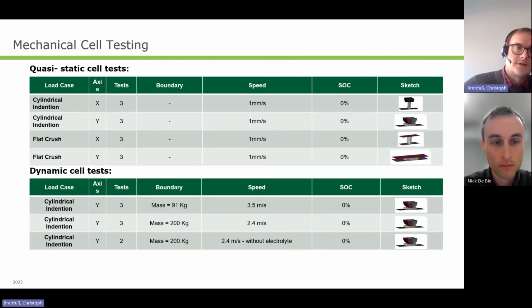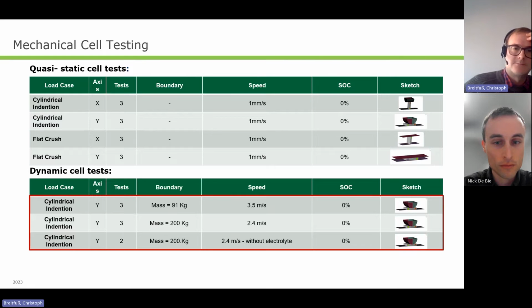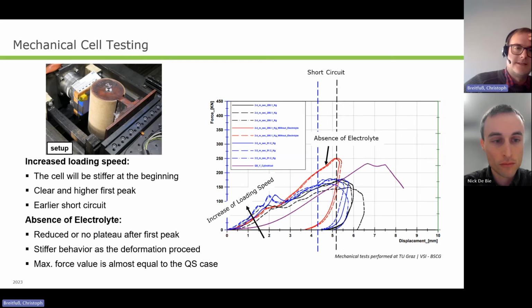Now we come to cell testing. Concerning mechanical cell testing, we did quasi-static tests and dynamic tests. Due to time reasons, I will put the focus now on the dynamic cell tests. We had different masses and velocities. The target always was to get enough kinetic energy to reach short circuit at every test. You can see here the test results.